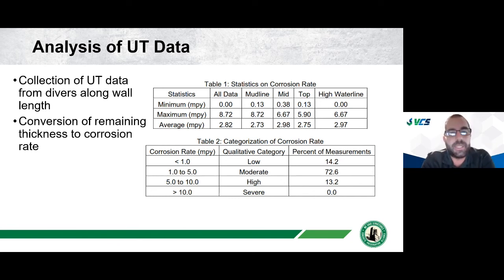Taking the UT data from underwater dive surveys, we can do some analysis of that data to understand deterioration over time. One of the things we can do is take the UT data and turn it into corrosion rates in mils per year. And we can look at the min, max, and average in different environments: at the mud line, mid-height, top, at the high water line. We can see the corrosion rate. We're losing about 2 mils per year, but in certain locations we were seeing 8 mils per year.